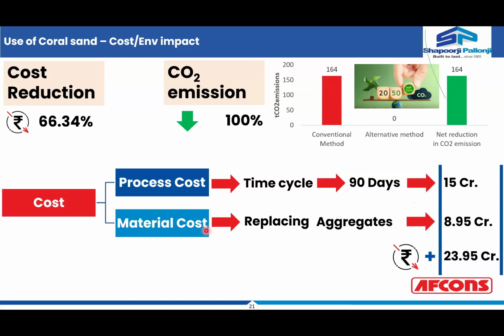Now, when you talk of process time, how do you calculate the process time and how do you calculate the material cost? It varies from process to process and location to location. In this particular case, when you talk of process cost, the process of intermixing of 10 mm, 6 mm and sand dust is being completely eliminated. So you don't need to mix and prepare a stockpile and test it for its suitability. Rather, you can directly lay the coral sand which is available there, and then do the in-field mixing of the cement and do the other activities.